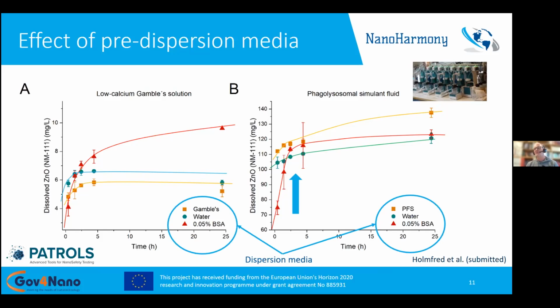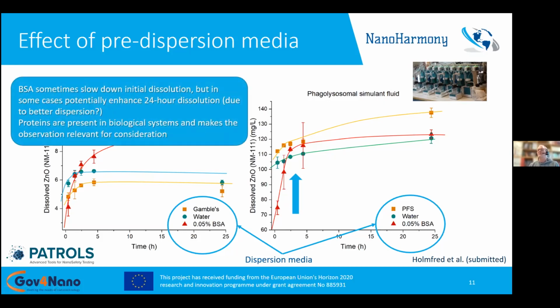And we have seen that in some cases we can increase solubility over time if we use the BSA water approach, and in other cases we delay dissolution, for example here in the phagolysosomal fluid, where we see immediate dissolution of NM111, for example, and slower kinetics for dissolution in the Gamble solution, which is in part related to the pH aspects. And we did that for a number of different materials, and we conclude that BSA sometimes slows down the initial dissolution, but in some cases also enhances the dissolution that we have studied over 24 hours in this experiment. And this could, to some extent, be related to better dispersion.